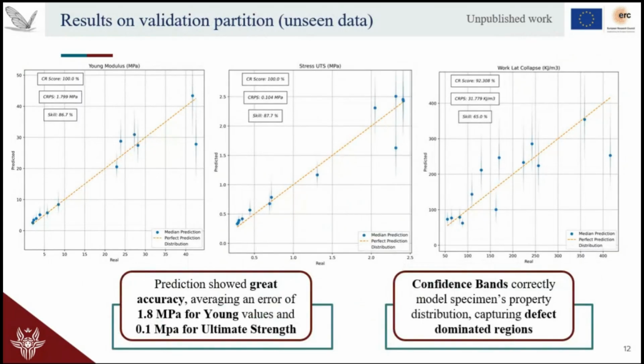As metrics, we have the continuous ranked probability score, which is a surrogate for the mean absolute error, but for statistical distributions. It collapses to the mean absolute error when we have a Dirac delta distribution, but it's very similar. So we have an error of 1.8 megapascal for Young's modulus and 0.1 megapascal for ultimate tensile strength. And that's pretty good because they're very, very low errors. And this neural network also, it doesn't look like it in the presentation because the colors are not right right now, but the confidence bands correctly predict the inner stochasticity of this process. So we have always the prediction inside the confidence bands.